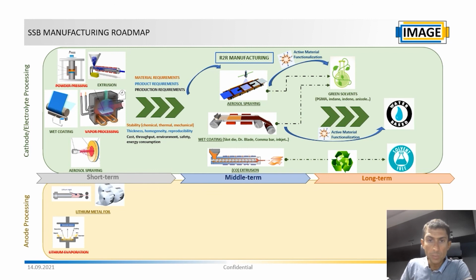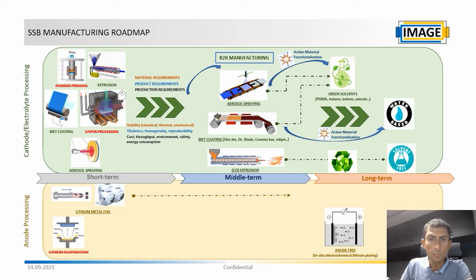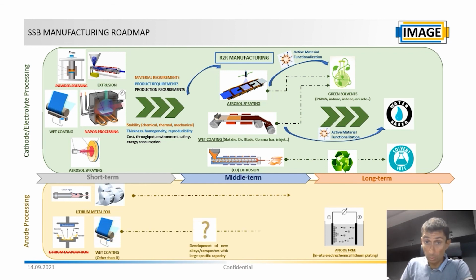At the anode level, lithium metal will be, without a shadow of a doubt, the preferred material in the short and mid-term, mostly processed from solid phase from the ingot, mainly extrusion and lamination, but it's also very promising the electrochemical deposition of lithium thin films from the ingot, and even the so-called anode-free approach with the in situ electrochemical lithium plating during the first formation cycles of the battery cell. Other approaches, such as wet coating, will perhaps be possible, provided the development of new alloys or composites other than lithium with also large specific capacities.